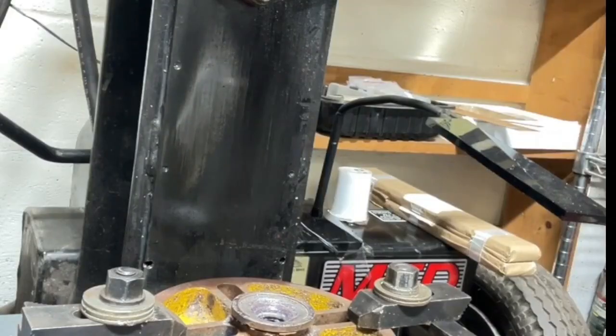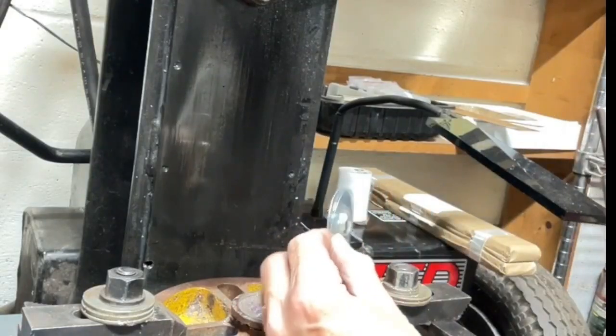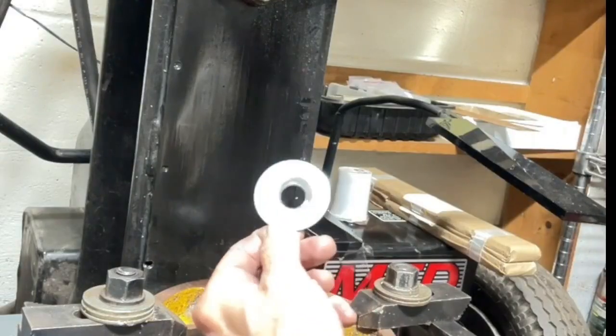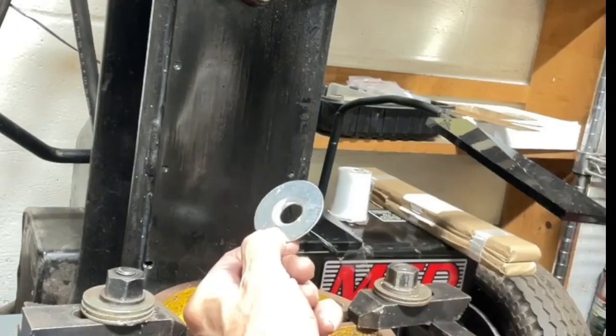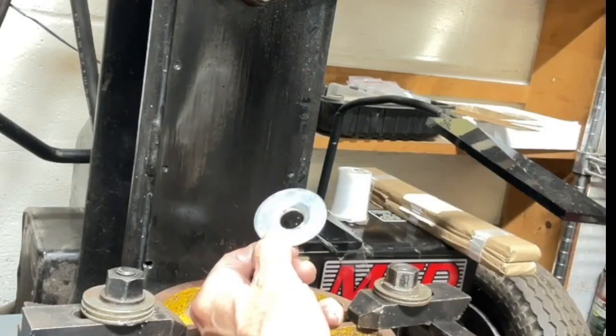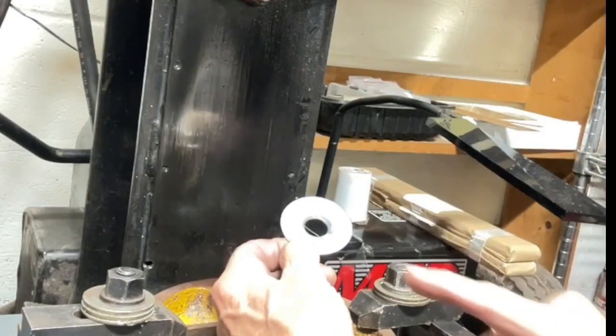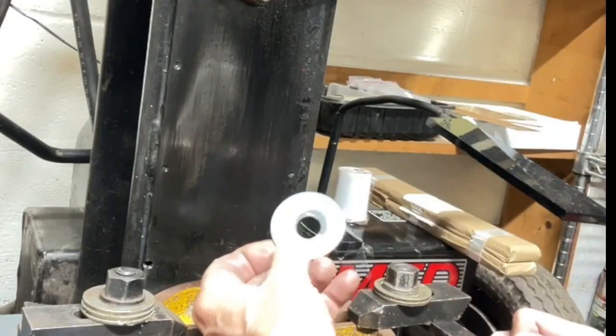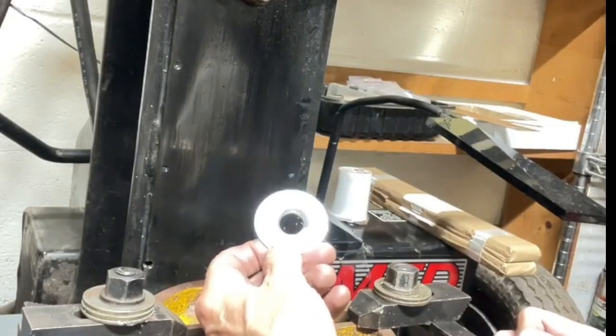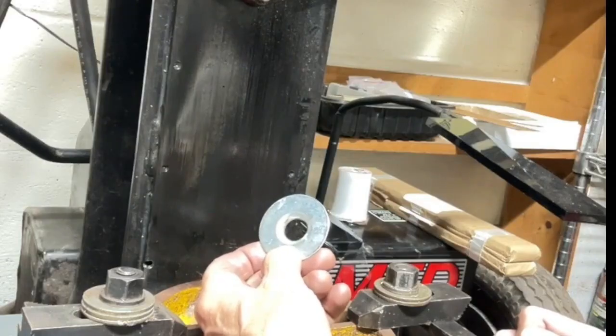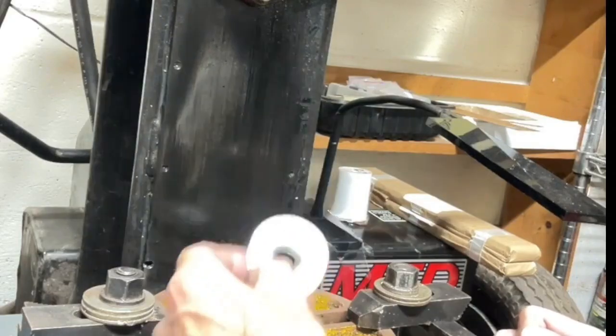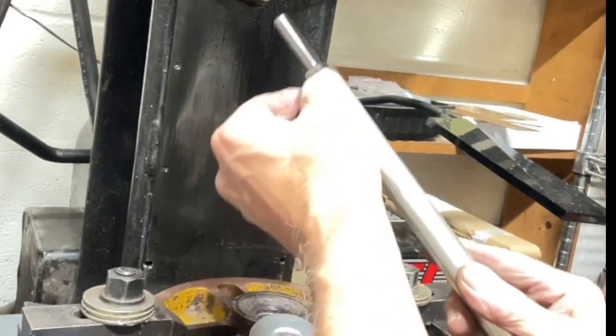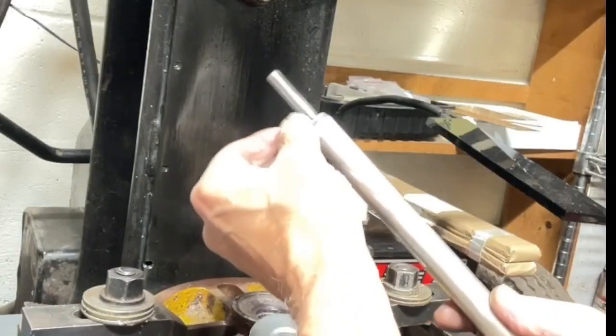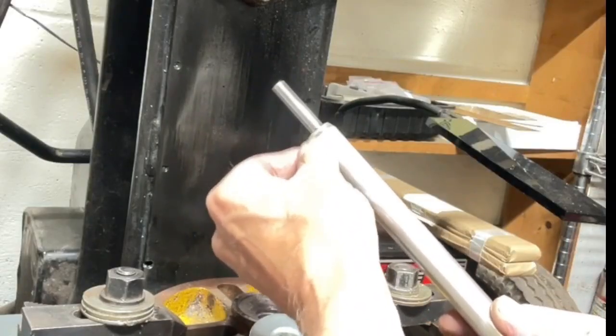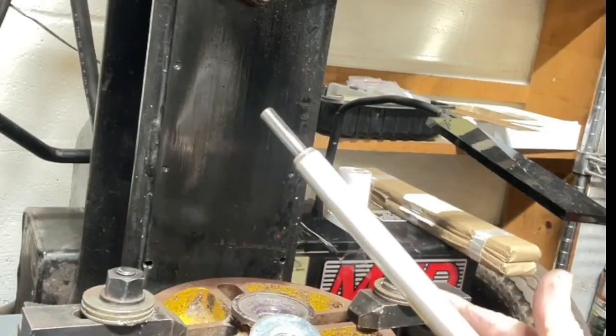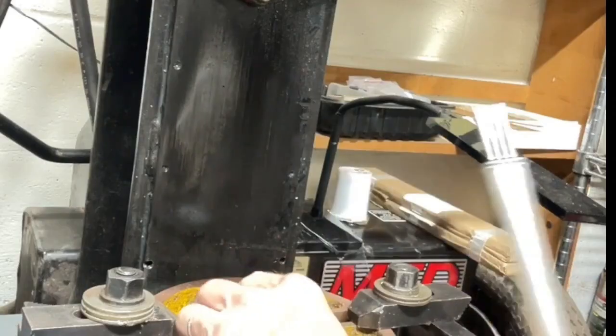The next step is drawing it through this cold rolled steel washer. As I mentioned before, I used to use a lead donut that I would make and machine the inside. And also I've used nylon or Delrin washers. And the problem I find with those is they don't draw as straight, and also sometimes they are prone to creating a pleat. And once there's a pleat at the very beginning, it irons that shape into the washer and it goes the whole length of the tube, and it can ruin a tube.